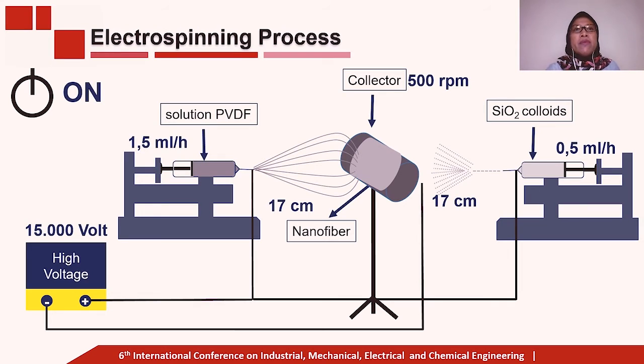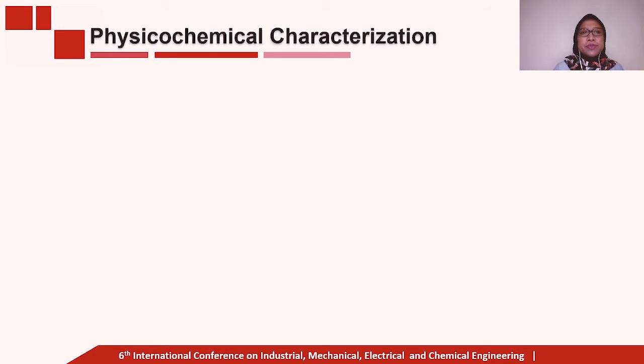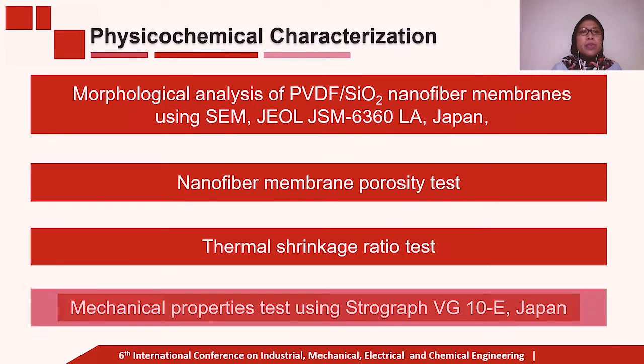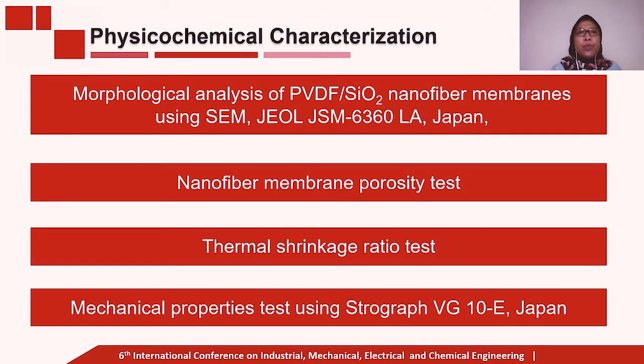The PVDF SiO2 nanofiber membrane results must be dried in the oven at 80 degrees C for 8 hours. The physicochemical characterization of PVDF SiO2 nanofiber include scanning electron microscope, porosity test, thermal shrinkage ratio test, and mechanical property test.